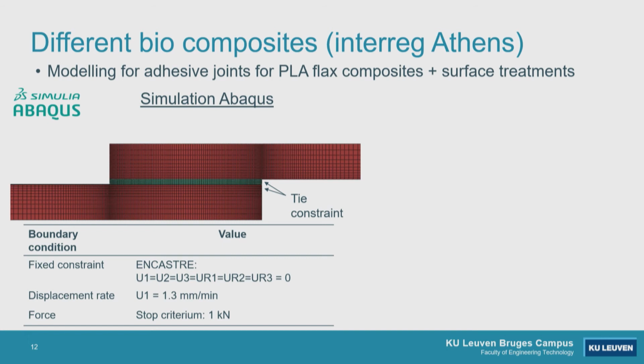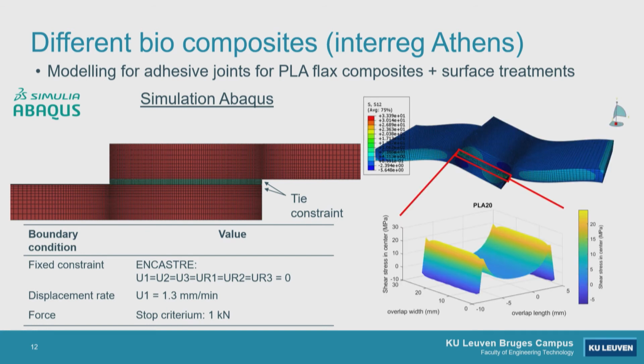Okay, before we go to the second one, also the type of work which is done in our research group within the framework of the Athens Interreg project is, for example, to model the whole behavior of a natural fiber reinforced material. And this is now using an adhesive, and just to see what type of stresses are occurring, and taking into account the local fiber orientation. So not assuming homogeneous properties of the two materials, but in that way you can see how these stresses are developing in the whole joint there. So of course, towards the end of the parts which are glued together, you have some higher stresses. But in this one, we take into account also local orientation of the materials which are joined together. Of course, this can also be done as soon as we have a kind of idea of the laser welding done in the research group of Professor Park. Then also stresses can be calculated.